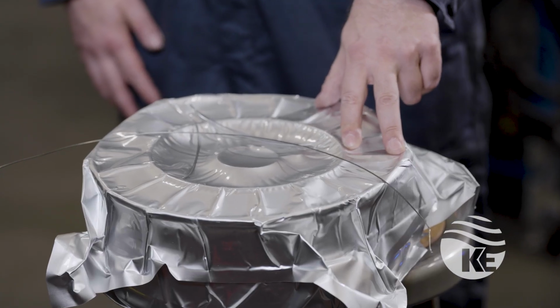The disadvantage of the flux core arc welding process is the fact that it is going to create a slag. So we're going to have to clean that off every single time, whether that's gas shielded or self-shielded. And we're also going to see the potential, as we see here, is that we've got a hermetically sealed wire spool. And that's part of the reason is that those fluxing agents that are in that tubular cross section have the ability to pick up hydrogen from our atmosphere. And that can induce hydrogen into our welds, which causes hydrogen-induced cracking. So that's a disadvantage.